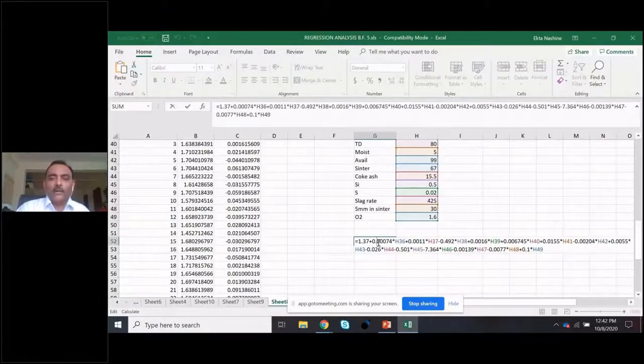These small things which are written: 1.37 is the intercept, as well as H36, H37, H38. When we see, these are different parameters. Suppose it's tapping duration or moisture percentage in the raw materials, or how much is the availability of the furnace, what is the sinter percentage in the charge, how much coke ash in the furnace, what is the silicon coming from the hot metal, how much sulfur is produced in hot metal, what is the slag rate, what is the fine size of sinter, and how much oxygen we are able to enrich in the furnace.